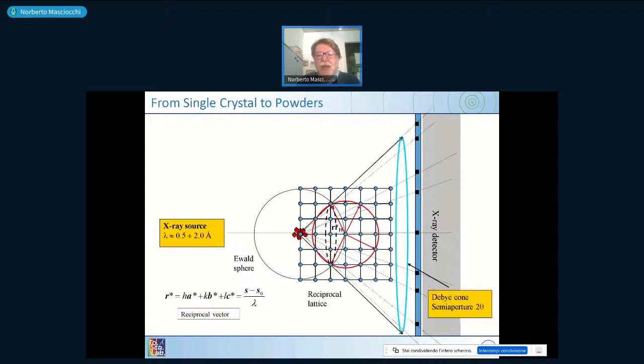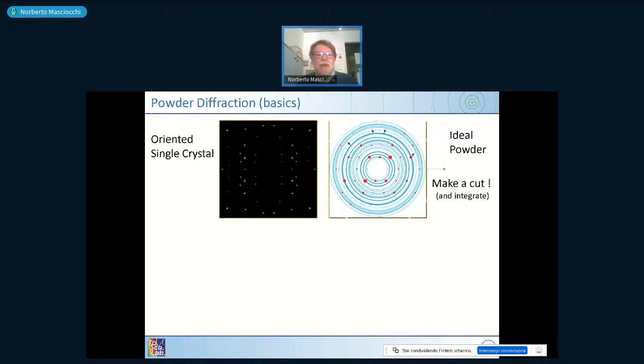It means that you have a cone of rays which comes out from the center of your sample. So not only with a single crystal you have spots, but when you crush a single crystal into small pieces, the spots are misoriented in an azimuthal orientation, and then for every distance from the center you have different rings. So the idea is that from a single crystal you have spots in space. From a single crystal to the right you have spots, the red ones, but then you average them out circularly. It's like making a hole in the center and having the red points rotate all around this axis, and then you have a set of circles.